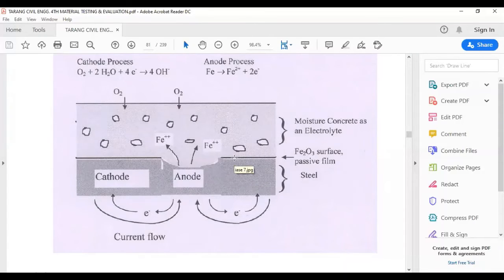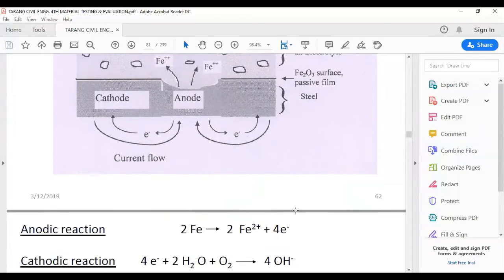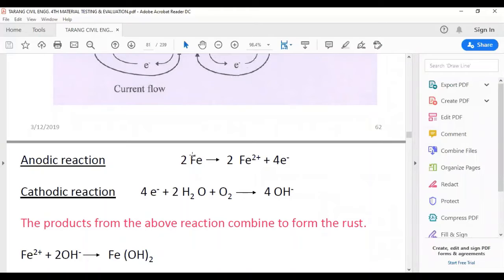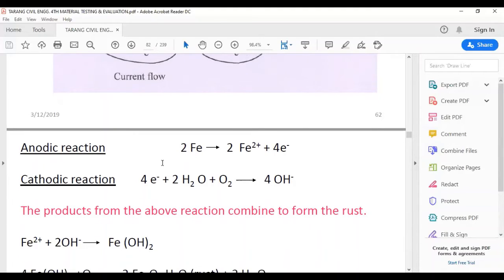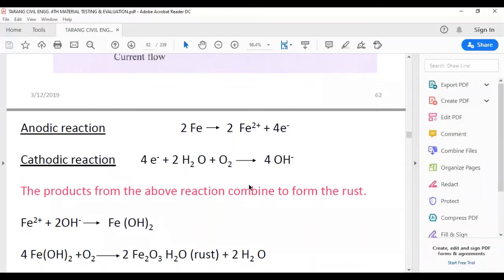This is the Fe2O3 surface passive film, which prevents corrosion initially. But once this passive film is broken, the corrosion starts to take place at a faster pace. So this we have already discussed. This is the anodic reaction. 2Fe gives 2Fe2+ plus 4 electrons. And these 4 electrons, when they combine with moisture and oxygen, they form hydroxyl ions. The products from the above reaction combine to form the rust.